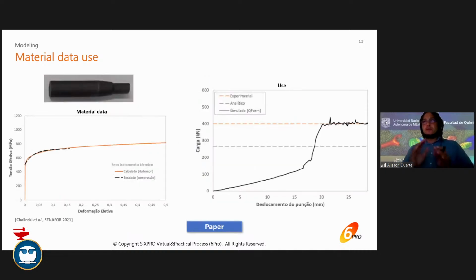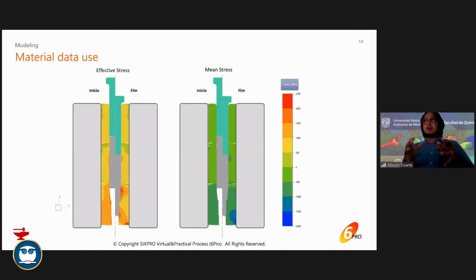All right. Also, it was a cold forging, so the matter of the dies is really important, because the dies suffer many stresses. So we also have to check at least the effective stresses in the die. You can see here, the die is assembled from 3 dies. So 3 dies make the tooling. And this company also has other dies here, shrink fit dies, so they can decrease the tensile stresses in the dies, which is very important, and also decrease effective stress.